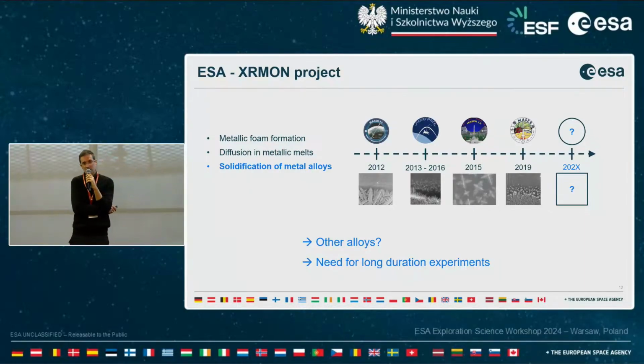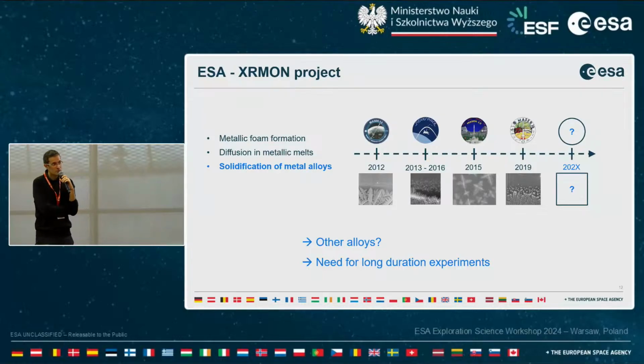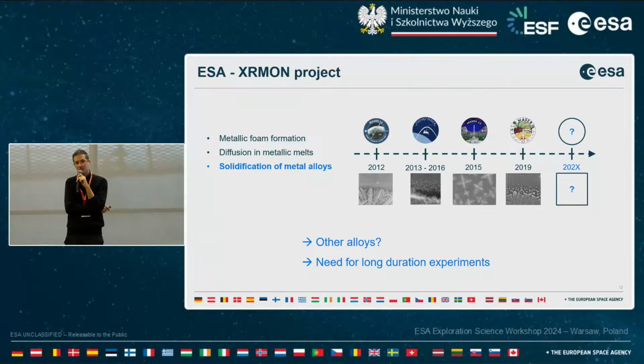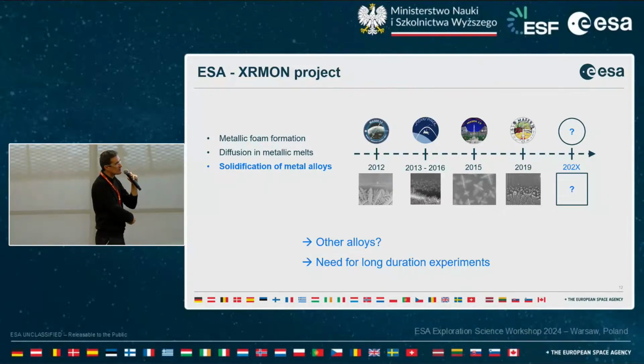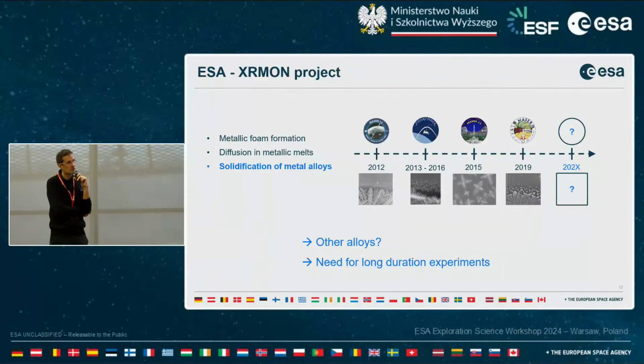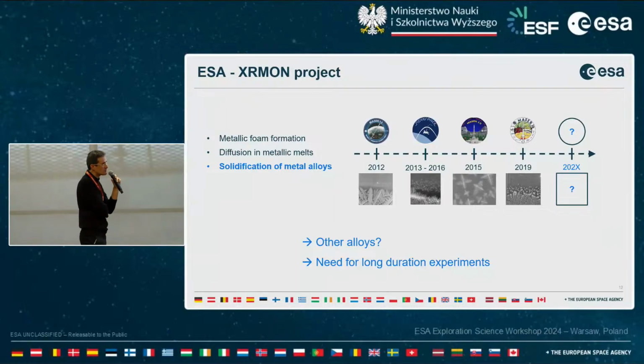And what did we learn from these experiments? Well, we should continue because it's very interesting, but also we should try to investigate other alloys. When I say other alloys, I mean different compositions, because so far most experiments have been carried out on aluminum 20 weight % copper, so it would be interesting to change the composition to 10 weight % copper or 4 weight % copper, which is closer to industrial alloys, or use different base materials such as magnesium. This is what I'm going to present after that.